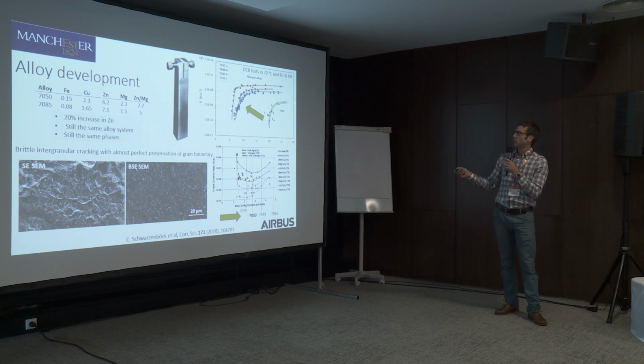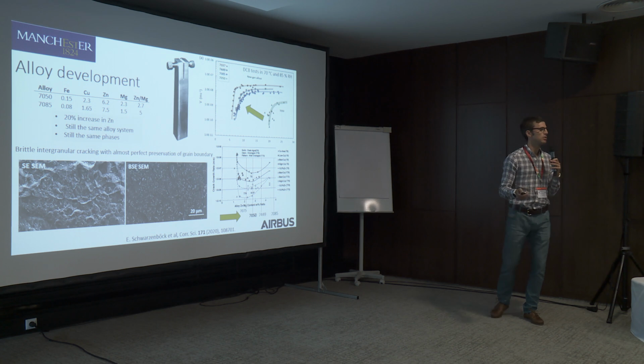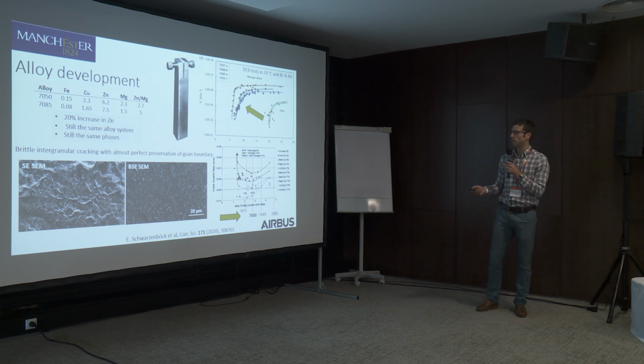And then when you actually reach what we refer to as a plateau, so the sort of maximum velocity that you can get at higher stress intensity factors, we also have a much lower velocity for this previous generation 7050 alloy. But for the new generation alloys, here shown 7037, 7449 and 7085, we've got a much lower threshold, so cracking can start at a much lower stress intensity factor. And then when it reaches its plateau, that velocity of the cracks is much, much higher as well.